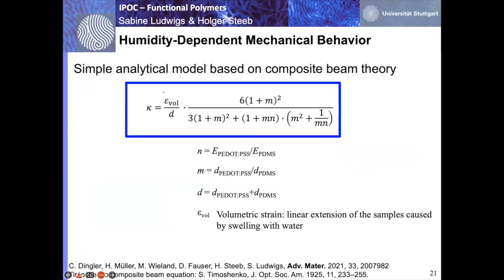This is the curvature, epsilon volume is the volumetric strain. D is the film thickness of both layers, so the film thickness of the PEDOT:PSS and the film thickness of the PDMS. And what else is in there? There's the elastic modulus, the Young's modulus of PEDOT:PSS and the Young's modulus of PDMS. Remember, PDMS is quite soft, and the Young's modulus of PEDOT:PSS changes as function of the relative humidity, as you will see in a second. And here, this M parameter is the thickness ratio between the PEDOT:PSS and the PDMS.